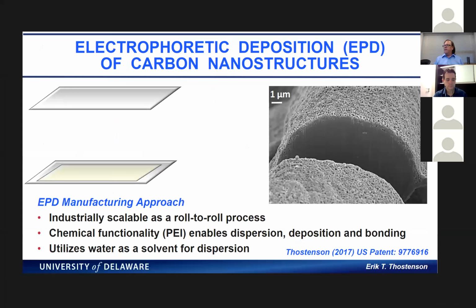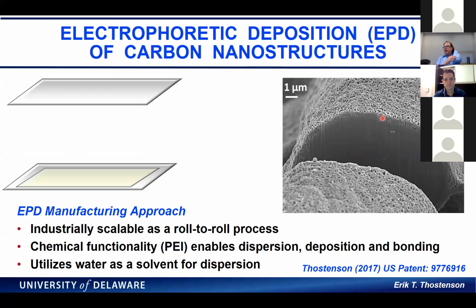Yeah, so if we come down to here, the amount of mass that you're putting on an individual fiber is almost trivial, because it's a very thin film. We can control the thickness, but typically it's a couple hundred nanometers, and it's porous, so it's open, not even a dense amount of tubes. So when we deposit onto a specimen, the mass changes by just a fraction of a milligram. So we're really using it in a small amount.